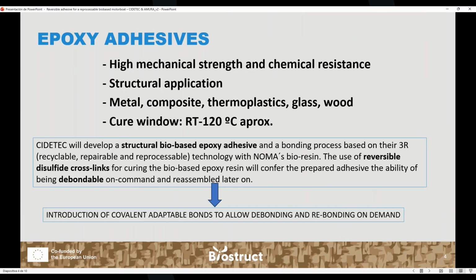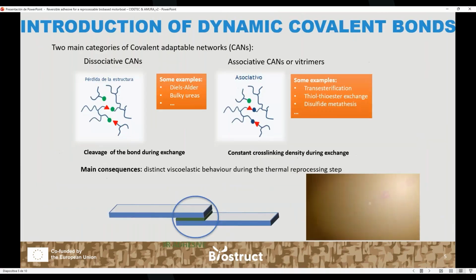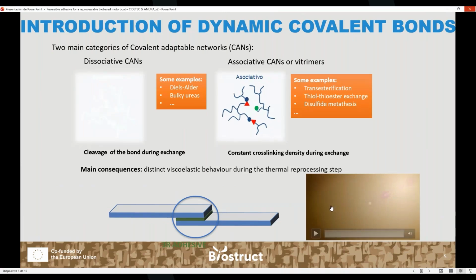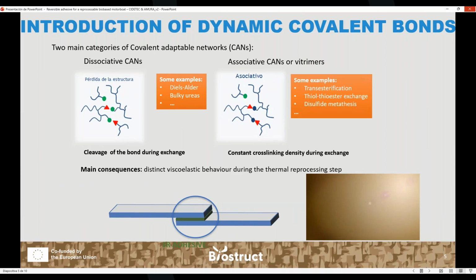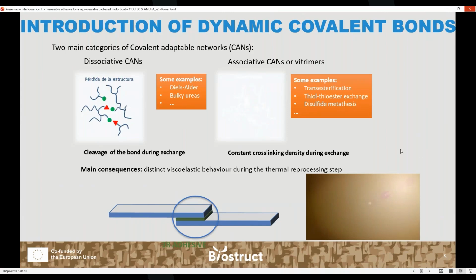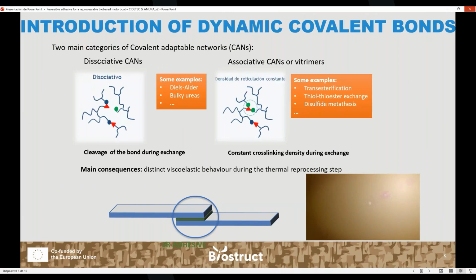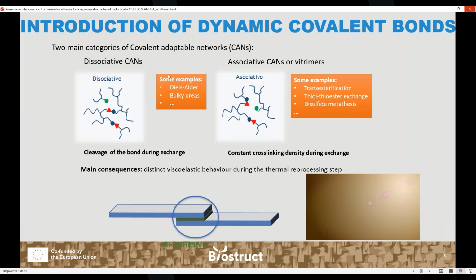Okay, taking this into account, in the BioStruct project, CIDETEC will develop a structural bio-based epoxy adhesive and bonding process based on our patented 3R technology explained before by Arad. In this case, to obtain the debondable adhesive, we will introduce covalent adaptable bonds to these epoxy adhesive networks. These covalent adaptable bonds are special because they are reversible, and we can differentiate between two different types, the dissociative and associative bonds.